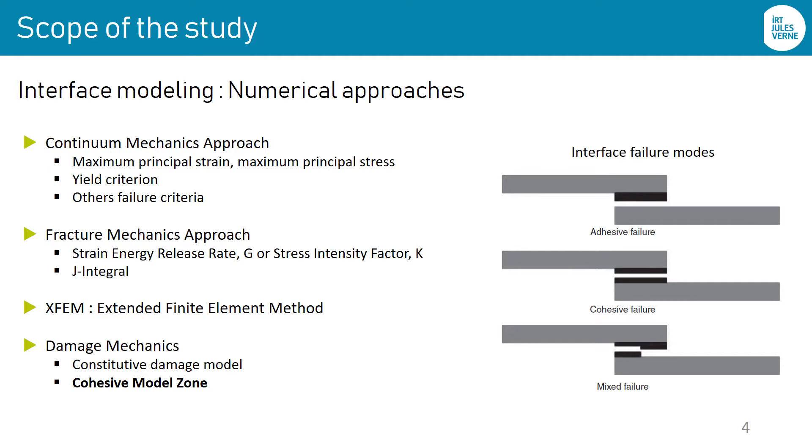Here we give a brief survey on the different methods used. The continuum mechanics approach based on a criterion of maximum stress or strain or on yield criterion or other failure criteria. Fracture mechanics approach based on the stress intensity factor or energy release rate assessment and the establishment of a relation with the crack growth rate.